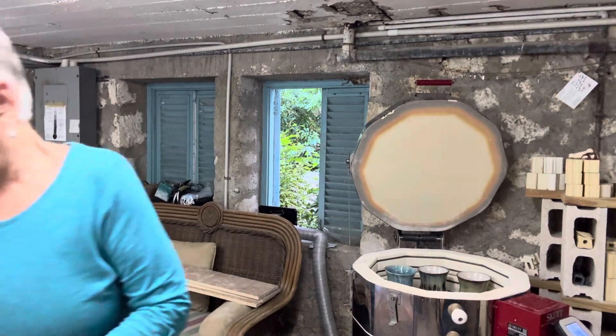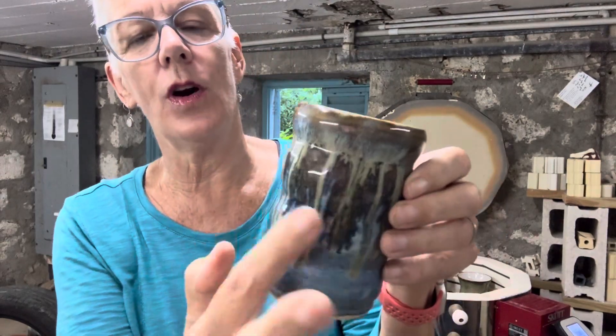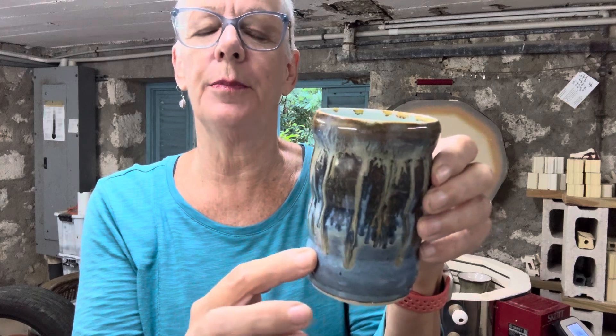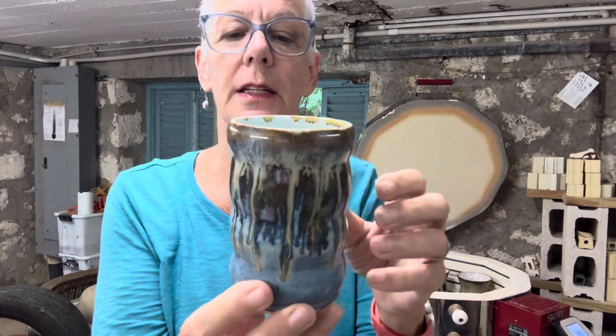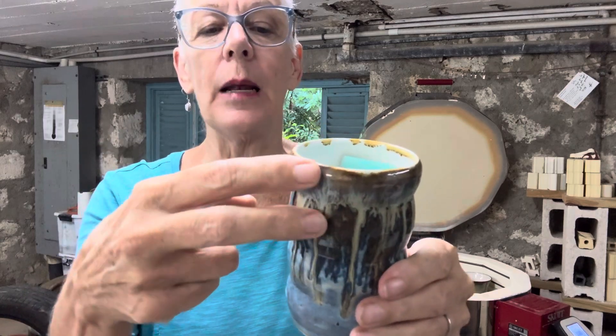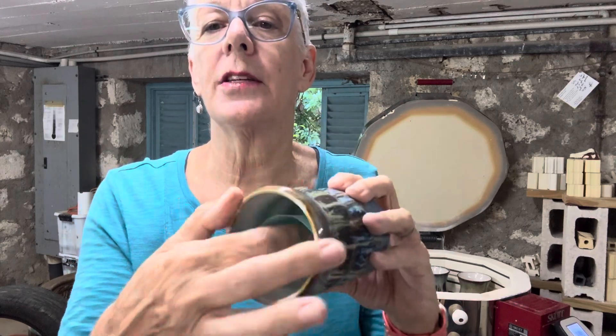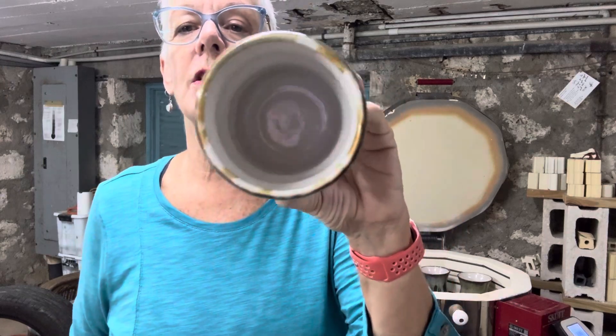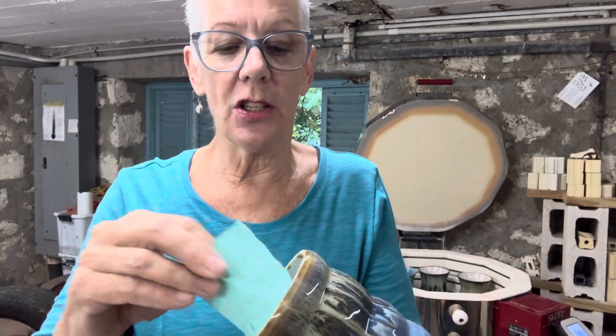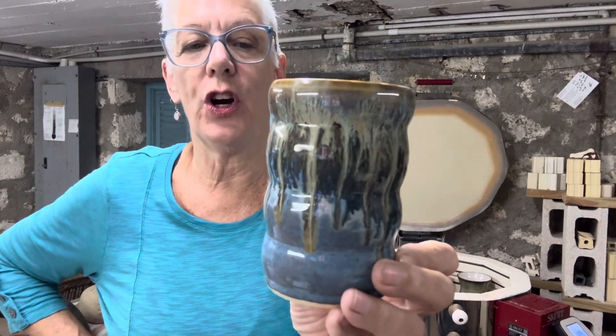Here's what I was excited to share — this is the original piece I was trying to recreate, what my client saw. It was four layers of Amaco Blue Rutile, then two layers of Mayco Light Flux about an inch on the rim, then about an inch and a half of Ancient Jasper, and then Ultra White on the inside. I have those notes right here. She saw this cup and said she loved the combination.